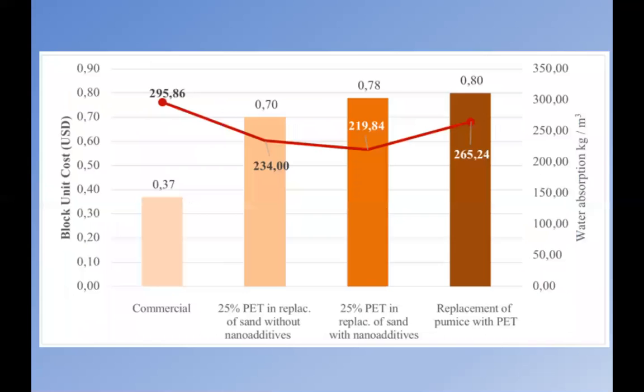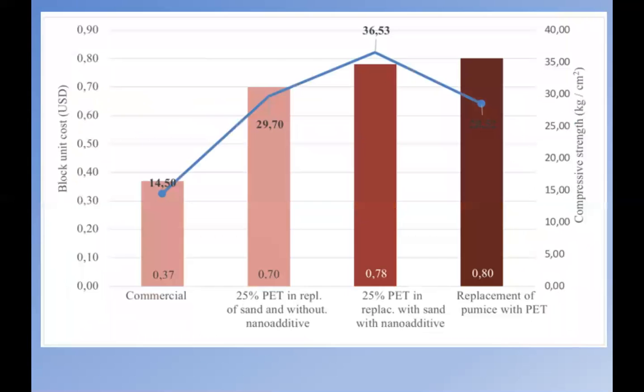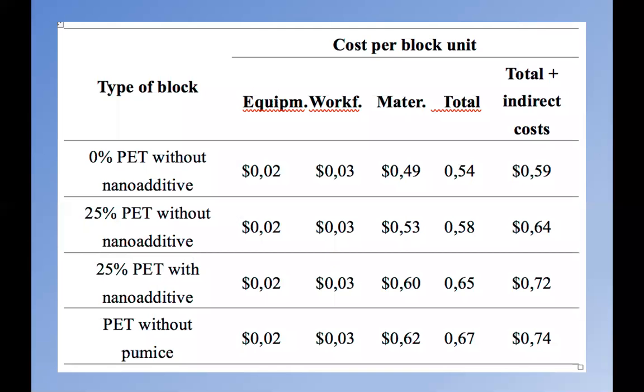However, a comparison was performed with compressive strength, water absorption, and cost in order to relate them to each other and determine the optimal dosage. This contains 25% PET in sand replacement and additive, and although it costs more, it generates the best results in both compression and absorption. However, it could also be considered the dosage with 25% PET in replacement of sand without nanoadditive, and its result is acceptable and the cost is lower.